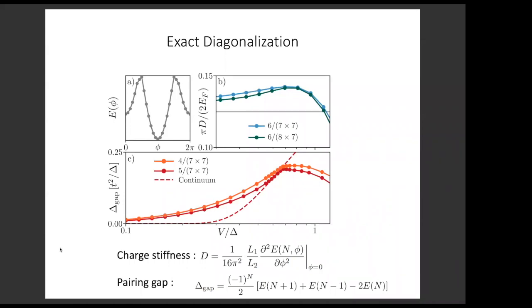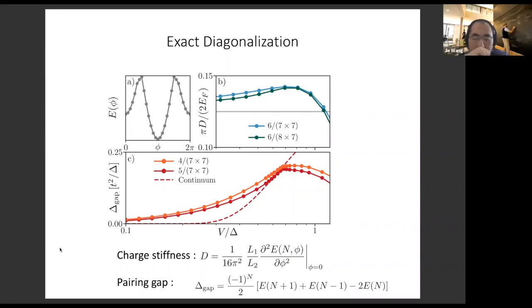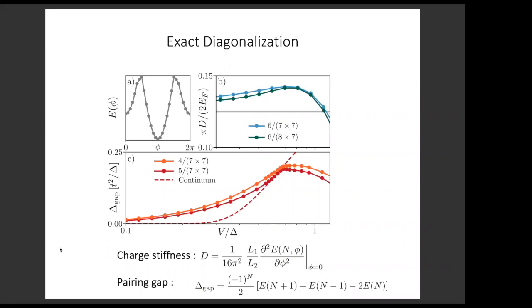And finally, in panel C, we show the pairing gap defined as the energy difference by adding and subtracting 1 electrons. We see the binding and the pair gap delta as a function of the interaction strength V. And again, you see that it shows superconductivity. Okay. And in fact, at small V, the coherence length is large, so finite size effect is strong. But you see that as V over delta approaches 1, it agrees. The exact diagonalization study agrees with the analytical results, which is a dashed line.